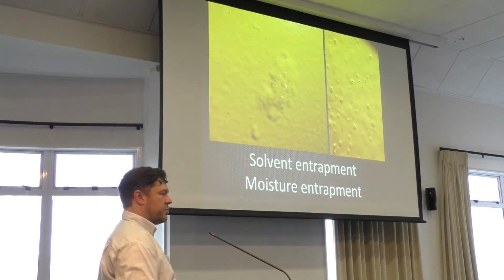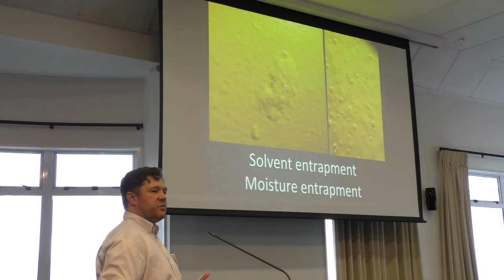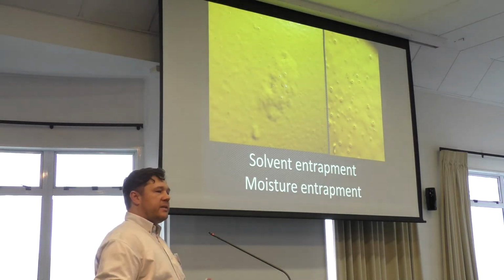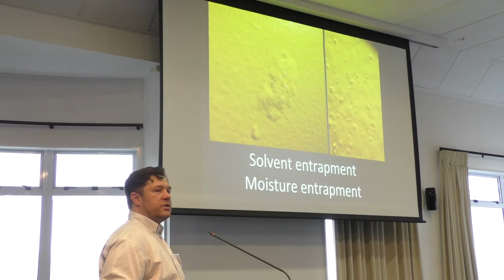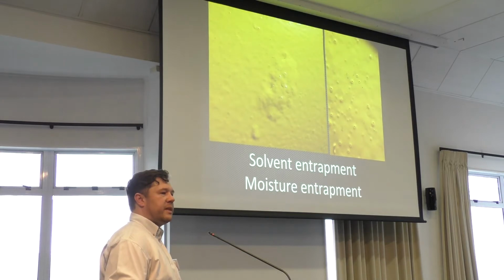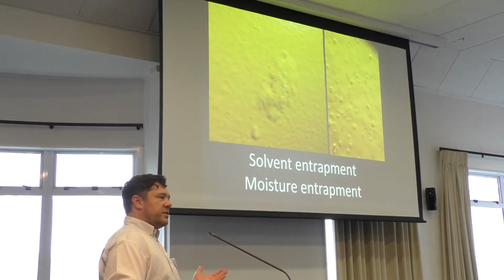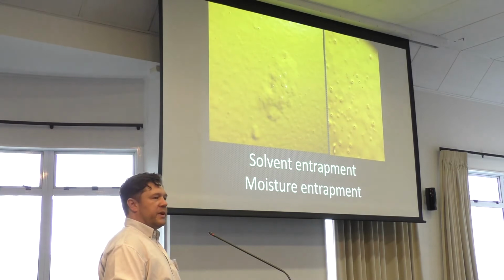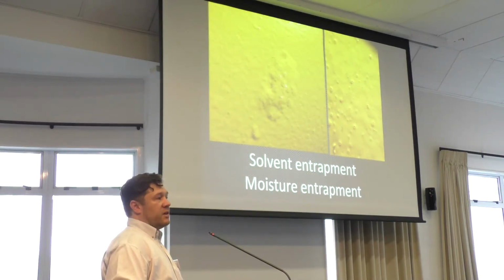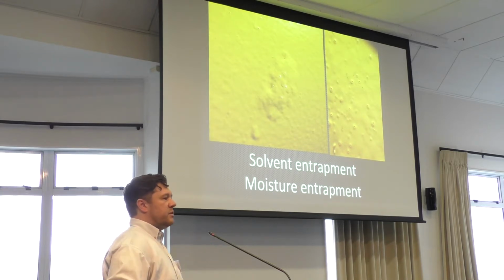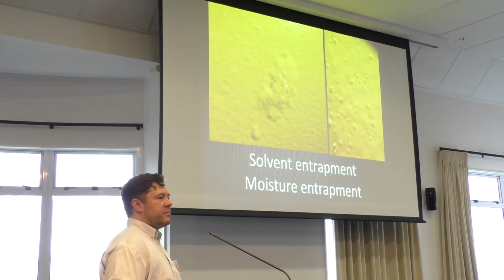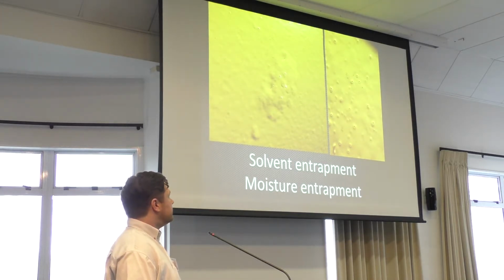One of the things to watch with metal spray is that after you put the metal spray on, if you leave it overnight and come back to put the sealer on in the morning, there's more than a good chance that the whole structure has gone below the dew point overnight and there's moisture then trapped in your coating. So you're relying on the penetration of the paint to push that moisture out, or you're trapping it in. It's kind of hard to measure whether it is particularly dry or not before you start. I mean, warming it or keeping it warm overnight is ideal if you're going to seal it in the morning, but really you should spray some and then seal it straight away, typically within 4 hours.